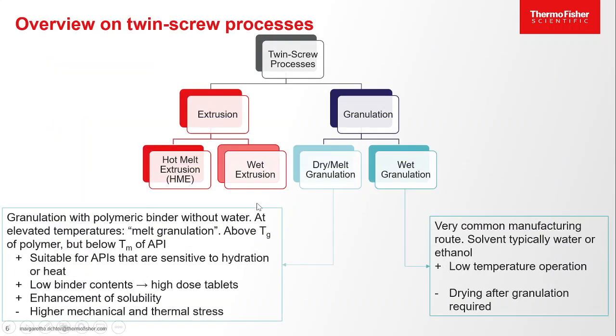So looking into the type of process, as mentioned, extrusion and granulation is possible, but granulation also divides into melt granulation or dry granulation, or into wet granulation. If you work without a liquid, so you do a dry or a melt granulation process, then you will have basically a polymeric binder and no water or any other solvent. And you perform the process at elevated temperatures. It doesn't have to be very high, but depending on the temperature, you can talk about melt granulation here. Basically, then you will have a temperature above the glass transition of the polymer, but in most cases below the temperature of the API. So you really just melt the binder in this case.